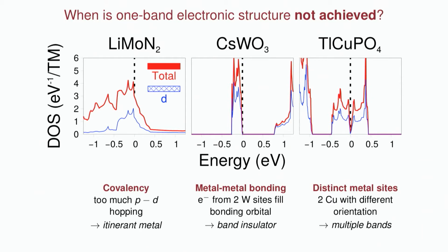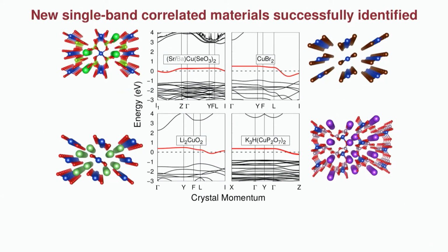And what happens here is that you have distinct metal sites with different orientations. So you've just broken the symmetry between different sites, and you get multiple bands. In this case, you get two different bands instead of one, the one that you were looking for. So I am happy to say that we do achieve a few single-band correlated materials. So we were at 26 before, and then we end up with 5.